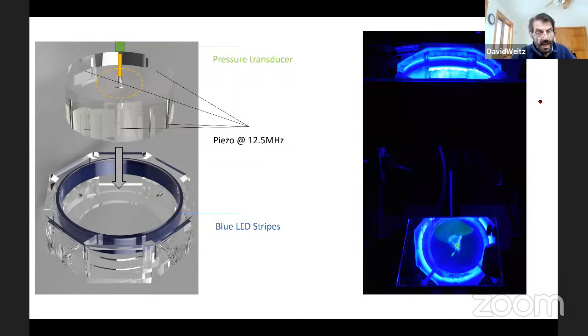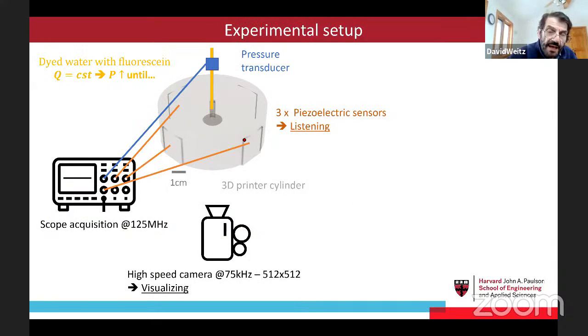One way, of course, that I showed you is this imaging. We've gone to different samples. There are circular samples, so they're easier to work with. But now we also add 4 regions on each side where we have flat samples, and we put transducers so we can actually listen to the crack. We can try to identify the acoustic sound that the crack makes, with the hope that we can then correlate what we see with the visualization, with the optics, which we have good time resolution, but not perfect optical resolution yet. We can correlate that with what we can hear and try and understand something more about the nature of the fracture in the material itself.